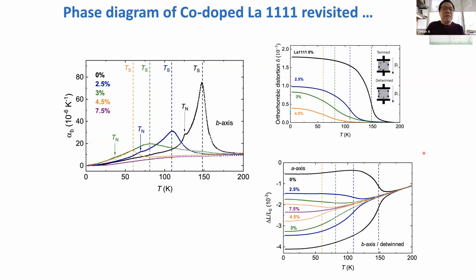And then we measured the phase diagram, and we did a broad spectrum of techniques to study that. And this is, let's say, a highest resolution measurement of the structure. So the dilatometry, where you see the temperature derivative of the lattice constants, you see the structural phase transition or the nematic phase transition here, and then you see the magnetic phase transition, even there, even the lattice constant, you can see that as a function of doping, the transition shifts to lower temperatures, as we know, and everything becomes very broad. So in particular, this structure phase transition becomes very broad if you start to dope it.